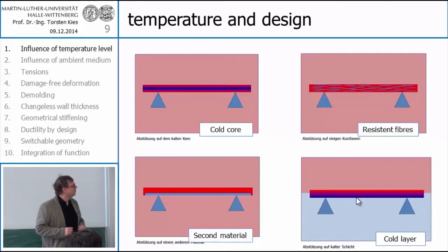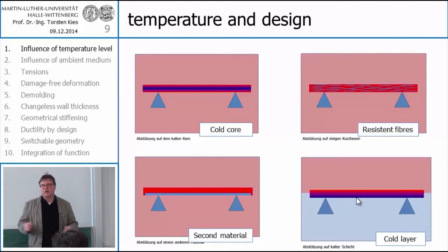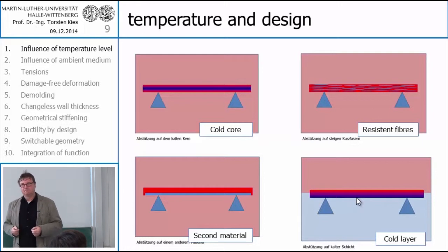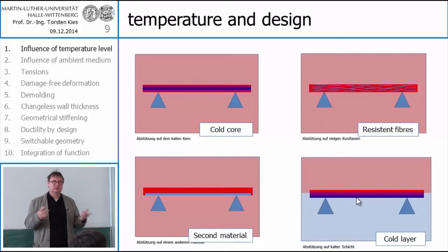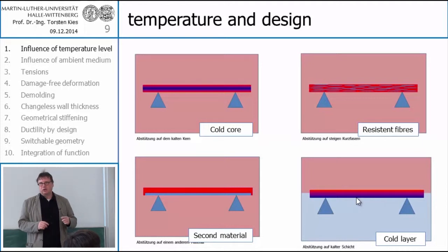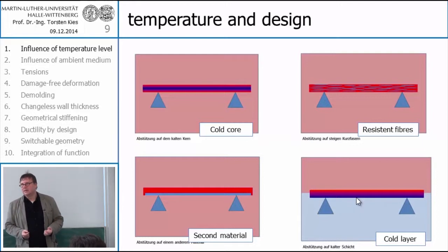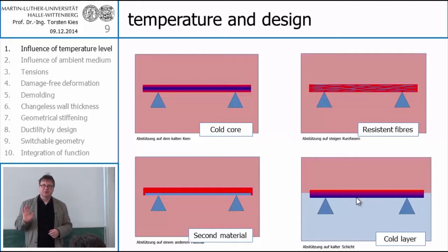The next slide shows us resistant fillers, for example, glass fibers also. They bring us about 5 degrees, what we can realize to go over the polymer melting temperature, the borderline temperature. Only about 5 degrees. You could say, oh, that's not much, but if you think what the prices are, if you need another and much better polymer, for example, a polyamide against a polyimide, then you have a big difference in the prices, and you say, okay, I take the filler. Also interesting is that the fillers realize a short time overheating better than a material without anything.